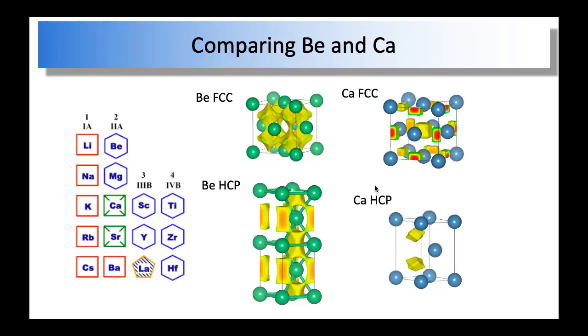Okay. On the other hand, calcium does not have that feature, and the localization of electrons at the octahedral site stabilizes the FCC, because the FCC has a larger Madelung constant, right? If you view this as positively and negatively charged ions, then the Madelung energy is lower for the FCC structure. So that's for alkaline earth metals.